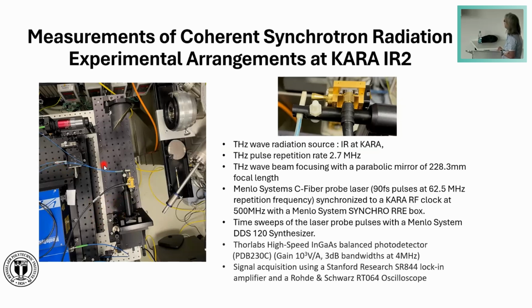Then we were probing it again with the Menlo Systems C-fiber laser at 1560 nanometers. This laser was synchronized to the KARA RF clock at 500 megahertz with the Menlo Systems Synchro box. And then we did time sweeps of the laser probe pulse using the Menlo Systems DDS 120 Synthesizer. The data acquisition was then the same. We had again the balanced photodetector, the lock-in amplifier, and we were visualizing the signal on the oscilloscope.